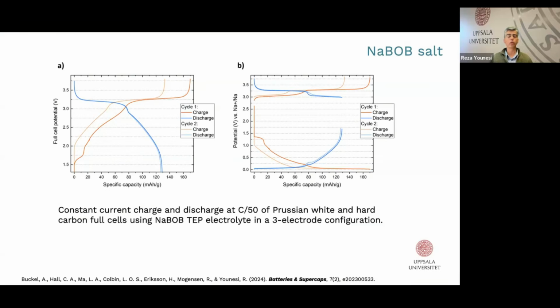One way is, of course, to use additives to optimize the electrolyte. By using additives, you influence the SEI formation. So if there's any additive, like VC for example, that decomposes before NaBOB, then the SEI becomes very much VC-based. Then we can basically address this issue that NaBOB itself cannot form an efficient SEI.